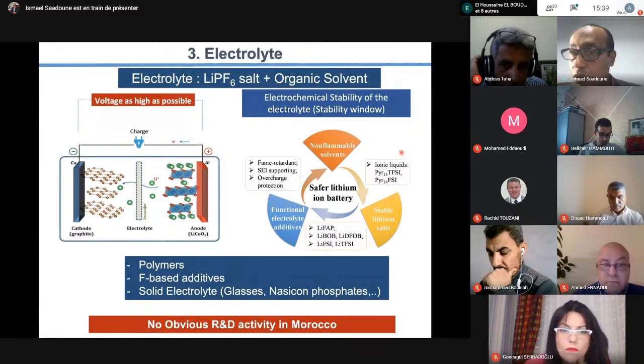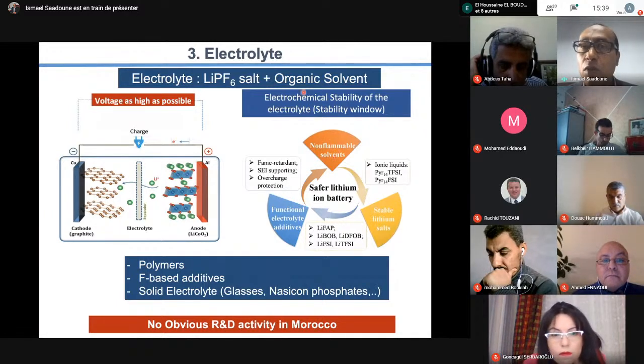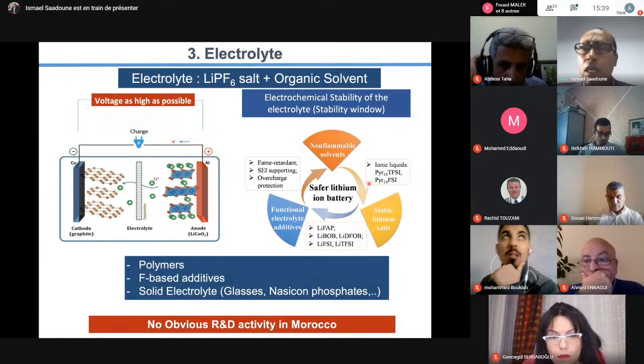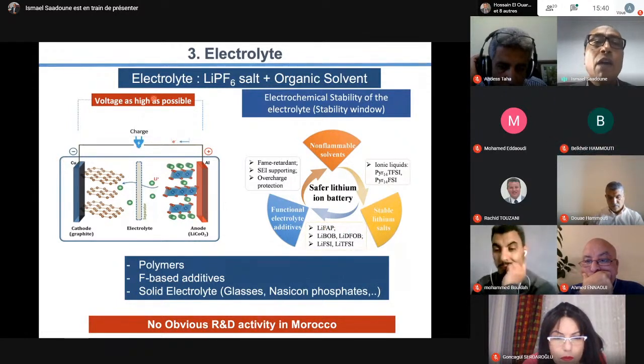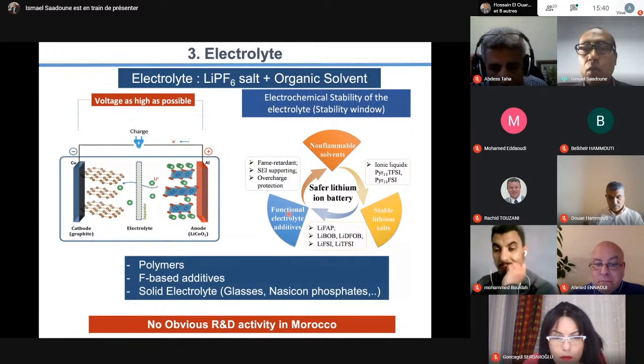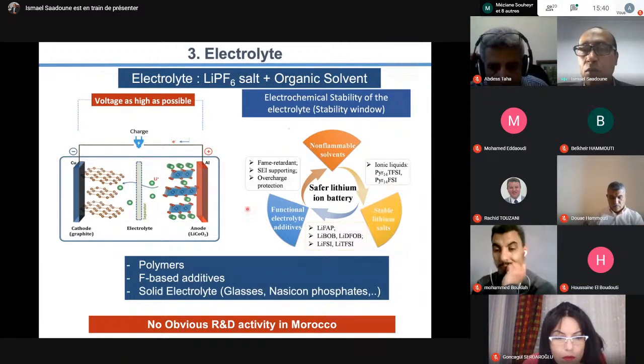So what people are doing now is to use some non-flammable solvent, because we have some organic solvents that can burn. We can use ionic liquid, for example. We can use some stable lithium salt in order to have higher voltage. We can use some additives. This is really the focus in electrolyte.